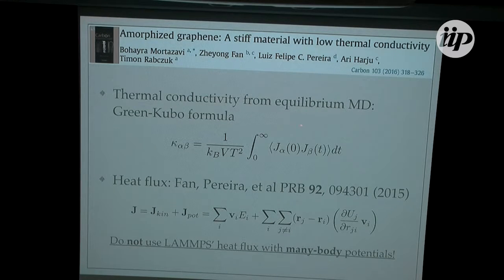Now, we went back now that Zhe-Yong had fixed the expression for the heat flux. We could use equilibrium molecular dynamics simulations, and there's a very practical reason here. We couldn't do non-equilibrium simulations because this thing is highly defective, and we are straining it. As you impose a temperature gradient, the system just breaks down. So we couldn't do non-equilibrium simulations.